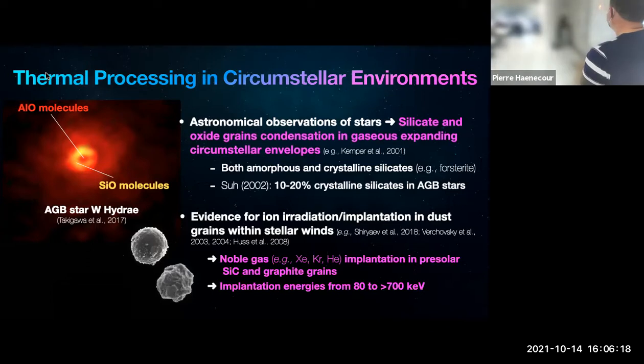Then if we look at other types of grains, carbonaceous grains, there is in stellar environments not just silicate or oxide grains that form, but also carbon-rich grains. So there are silicon carbides or graphite that actually condense in stellar environments. And studies of those grains from meteorites have shown that they have really large abundances of noble gases, showing that they basically had implantation of noble gases into the grain, showing that they were irradiated by high energy particles.